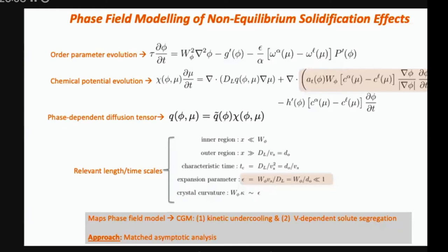From these equations, can you find a length scale for the dendrites that are formed? Yes. So after you tune the model to mimic something at the interface and match some material parameters, the kind of name of the game is always, can you get some length scales that emerge based on the process parameters, like the physical parameters. The one scale that always stays the same is the interface width. That's an atomic structure. But then the emergent scales really depend sensitively on how you cool and the type of alloy chemistry you have. And there are ways we can map them, we can fit them to different models and see which model is better. So to date, there is no single analytical model that fits the numerical data or the experimental data.